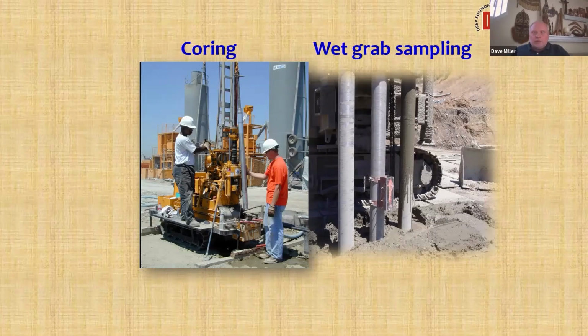So here's a shot of the difference in coring and wet grab sampling. Coring uses conventional coring to achieve samples after you've achieved a sufficient strength, but obviously prior to the testing date. You can't test a 28-day core if you didn't core it until 35 days. But a lot of projects, because of that difficulty, some of the strengths are older, but the important thing is, are you meeting the strength? Are you meeting the intent of the project? Okay. So cores can be problematic because the material is relatively low strength. It's hard to core. Wet grab samples typically have a sample box mounted to the auger and sent down to retrieve the sample. At shallower depths, you can separate the sampler from the drilling and put it on a beam or something like that.